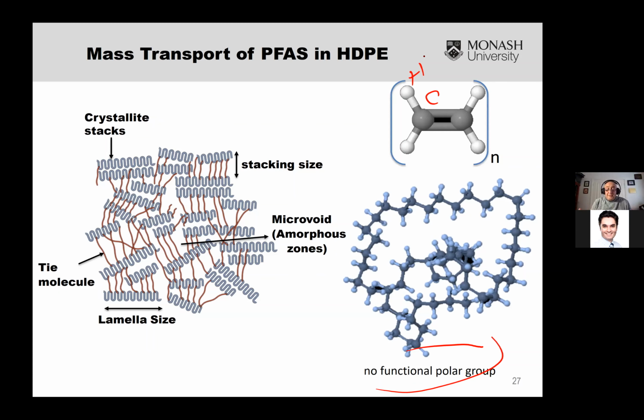Polyethylene is known to be less resistant to non-polar organic substances such as aliphatic and aromatic hydrocarbons, which can really diffuse through it. And there's a good body of work on that already available. In contrast, polar molecules will tend to exhibit lower affinity with polyethylene and will certainly have a lower diffusion rate through it.